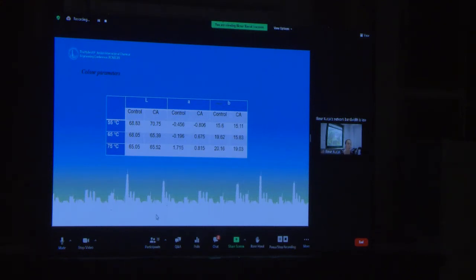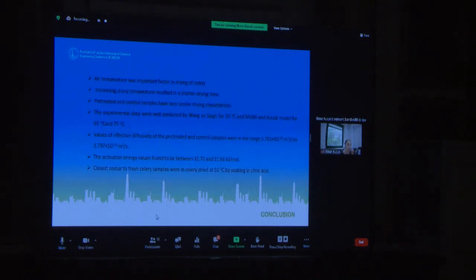And then, in conclusion, air temperature is a factor in drying of celery. Drying temperature resulted in pretreated and control samples having very similar drying characteristics. Experimental data were fitted best by the Midilli model at 55 and 75 Celsius. The effective diffusivity of the samples was in the range of 1.2 to 3 times 10 to the minus 10 per second. Activation energy values were found to be 22.3 and 30.66 kilojoules per mole. Closest color to fresh celery was in celery dried after soaking in citric acid. Thank you.